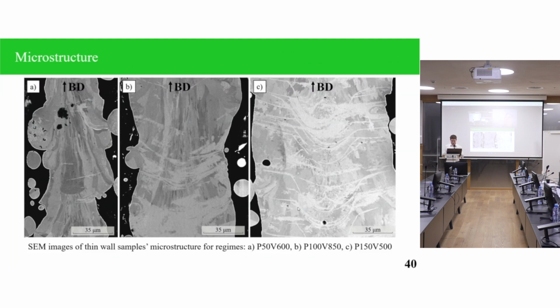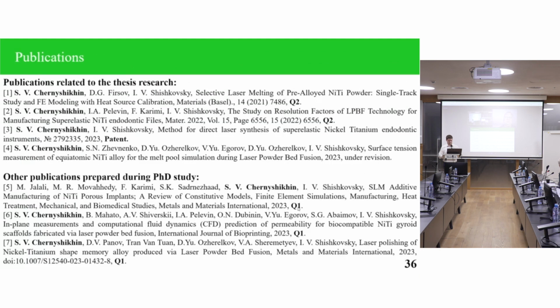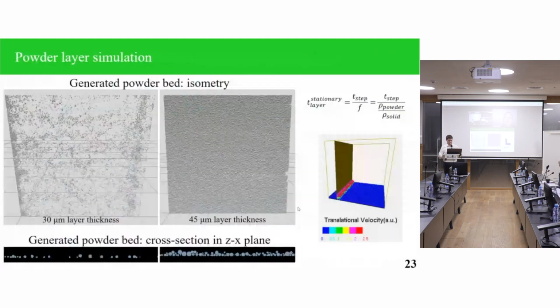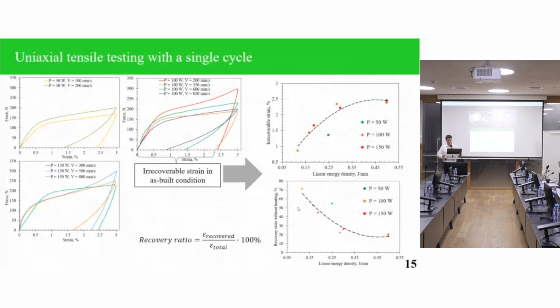The other question I have is, shape memory alloys often exhibit the Mullins effect or Patrikeev-Mullins effect, where with consequent cycling, typically during the first cycle, the stress of the martensite transformation plateau is higher compared to the consequent tests. And in your data, you showed stress strain curves or load strain curves to failure. How many cycles did you try when you were doing the testing?